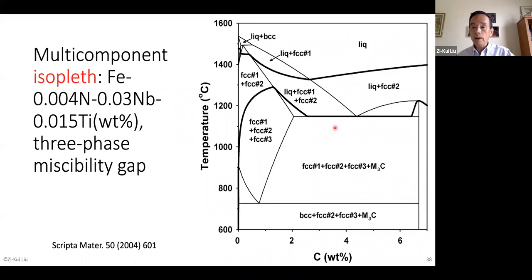And also very important, right, you want to avoid formation of the FCC2 at high temperature or from the liquid, because it becomes very coarse. So that means you want to see where you can avoid it. You can avoid this phase forming from the liquid phase. So you can see that...